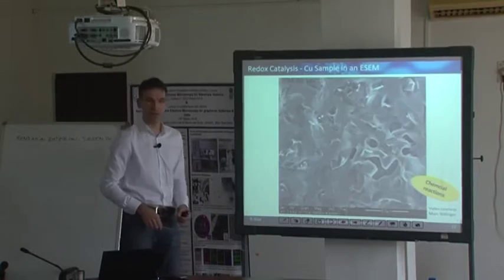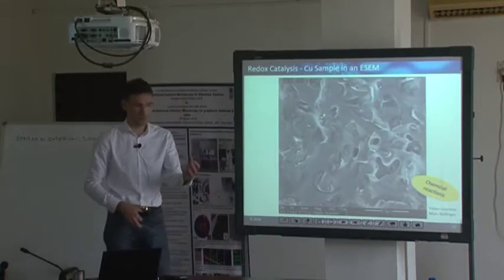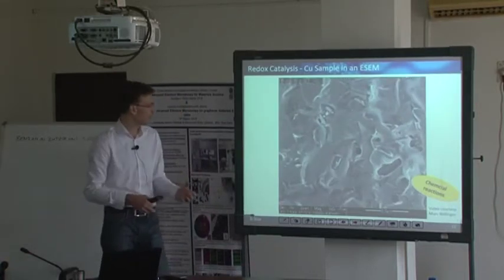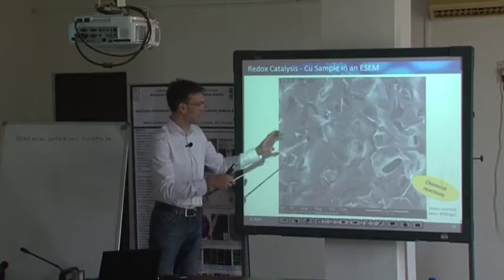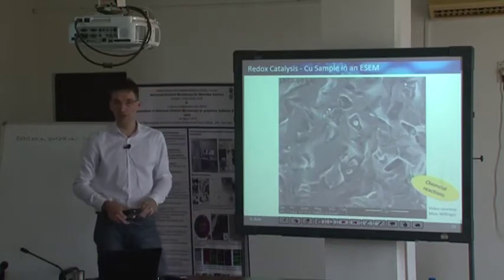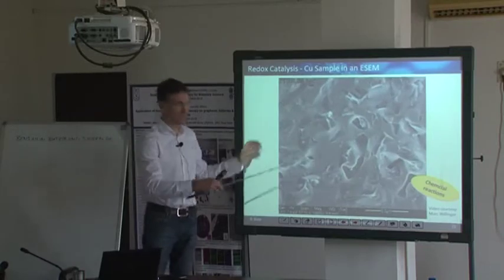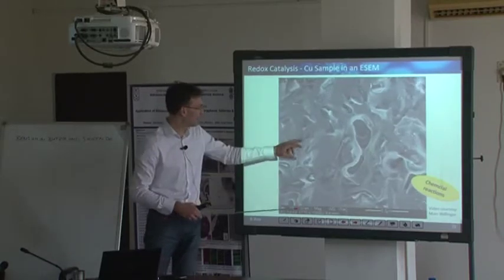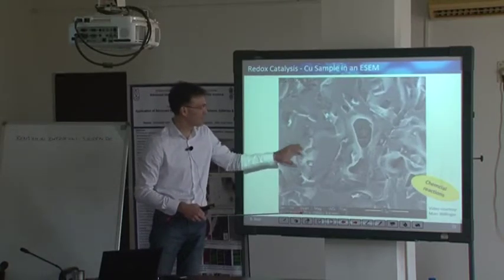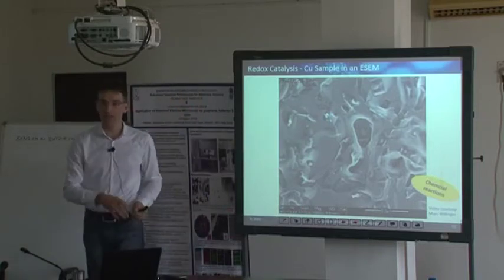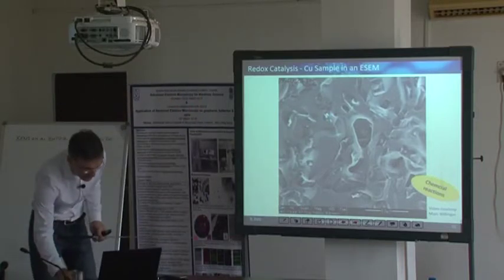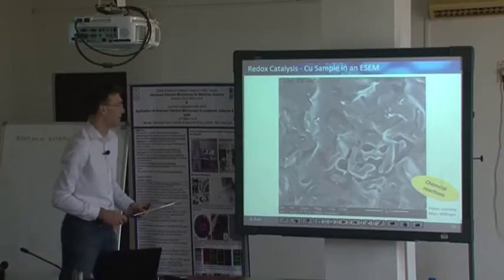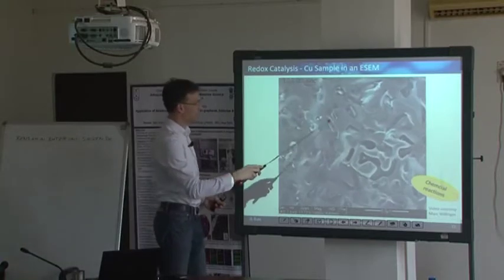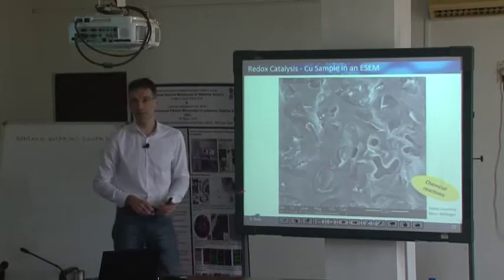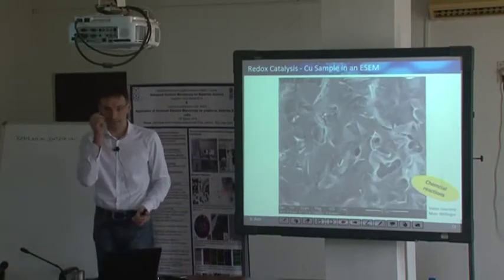So it's not that you have certain oxidation and reduction on the atomic scale. This is a pretty severe change of the morphology of a whole surface just during such a reaction. You see some areas which get oxidized, some areas which get reduced, and this is an interplay between local oxidation and reaction and reduction of such a catalytically active surface on a larger scale.